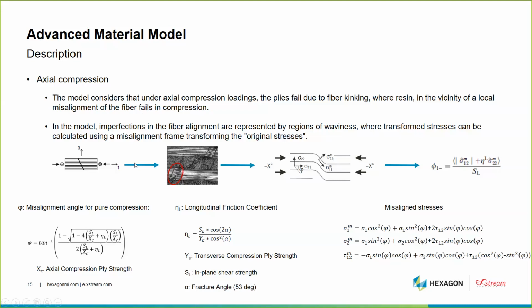In the failure model, the failure model proposes a methodology to compute this angle of misalignment. This is what is noted phi here, which is based on material properties or lamina properties. You see that here we use the XC to compute the misalignment angle. We also compute what we call the longitudinal friction coefficient, which also relies on material parameters.